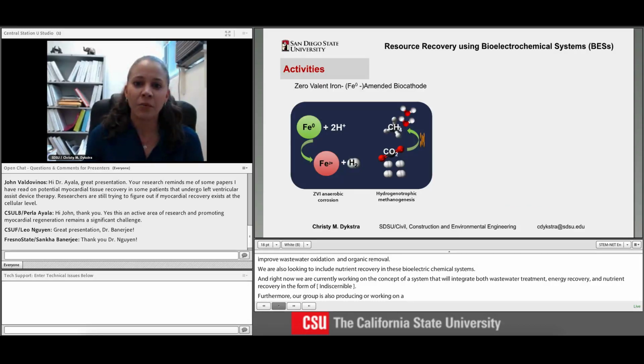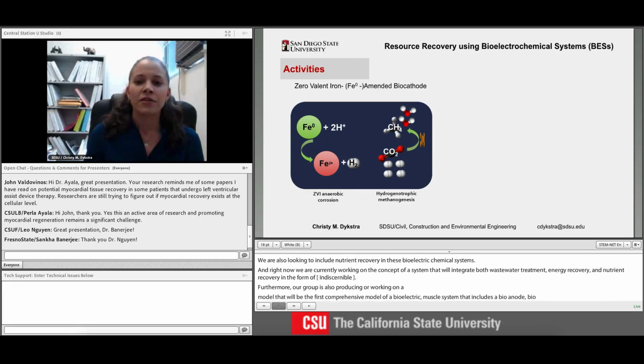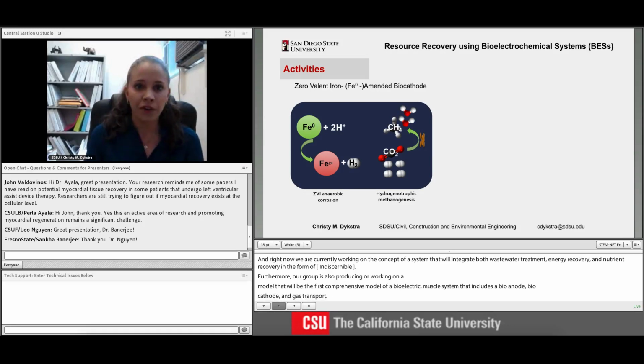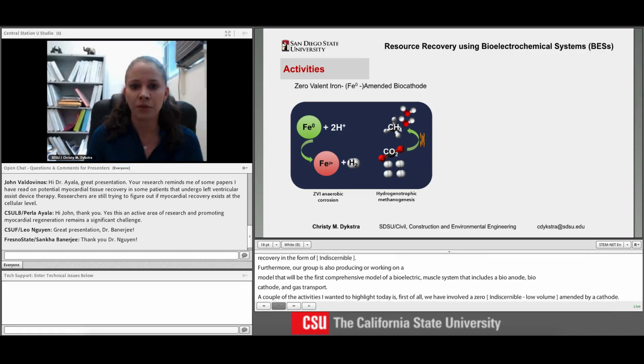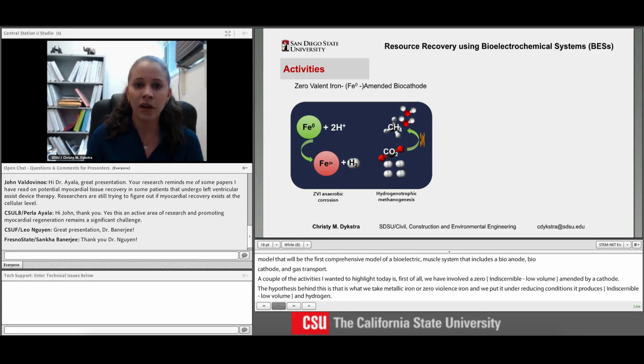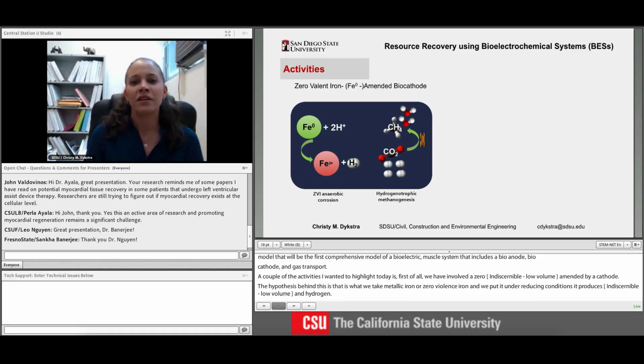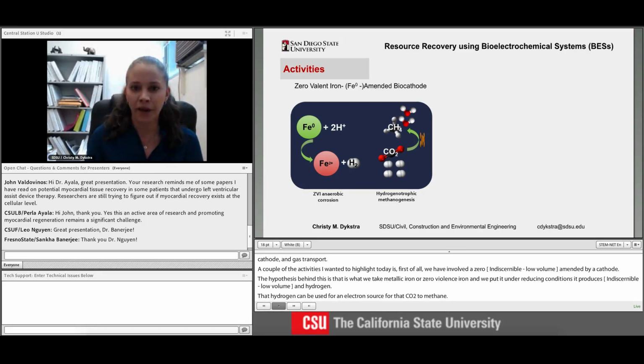So a couple of the activities that I wanted to highlight today is, first of all, we have developed a zero-valent iron amended biocathode. The hypothesis behind this was that if we take metallic iron, or zero-valent iron, and put it in the biocathode under reducing conditions, it produces ferrous ions and hydrogen. And that hydrogen can be used as an electron source for the reduction of CO2 to methane. Indeed, the microorganisms that do this in the biocathode are very happy to use the hydrogen and improve the methane output using a simple addition of iron.